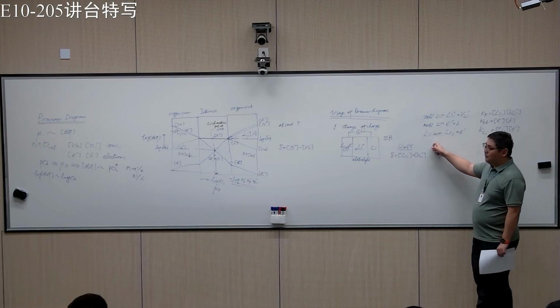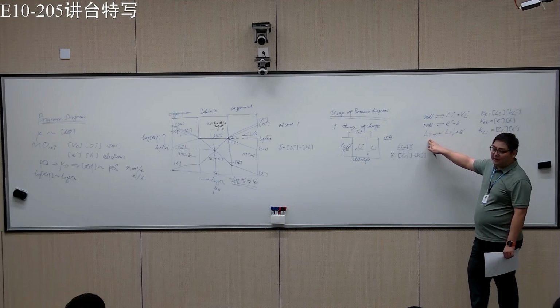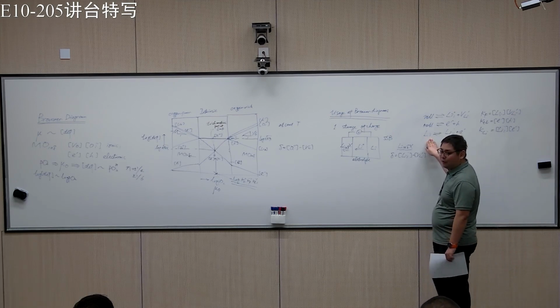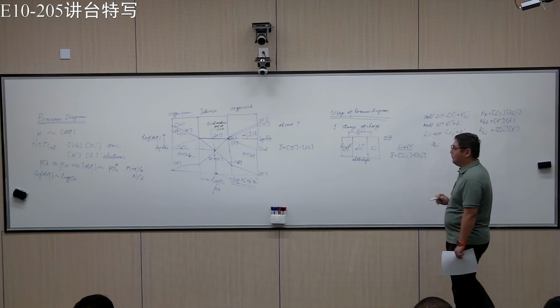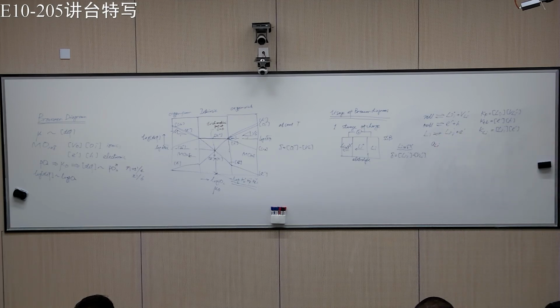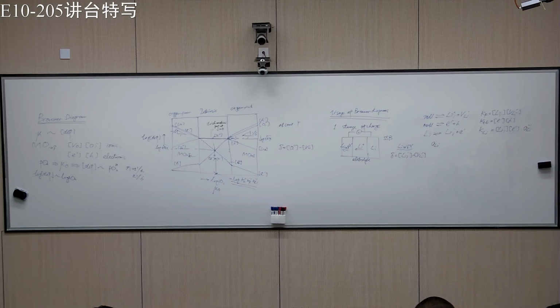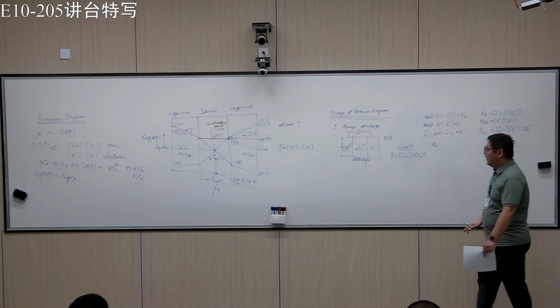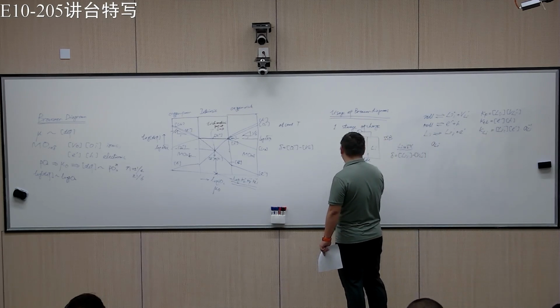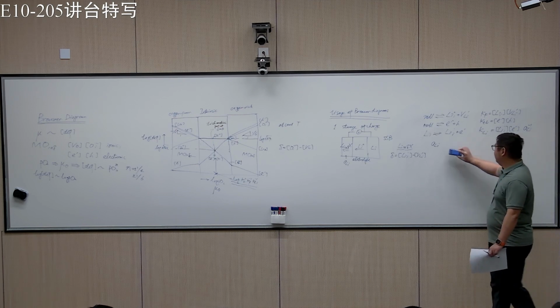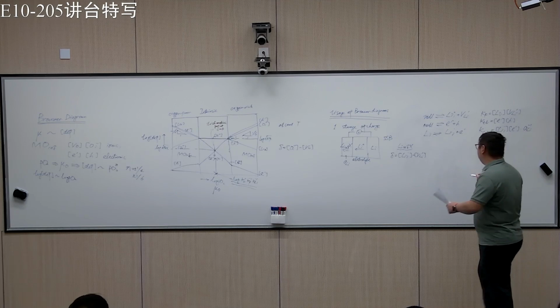Sorry, I've got a very important thing. We write lithium here. What decides the chemical reaction is the amount of lithium, or the chemical potential of lithium. So here you write the activity of lithium into the equation. If you change the activity of lithium, you change the concentration of these defects in these compounds. Of course, you have the charge neutrality.